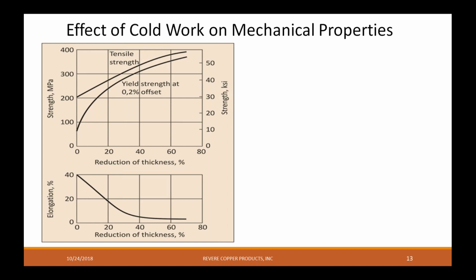And then your elongation at the same time is going to go down. So that's your ductility. So as the metal gets harder, it becomes less ductile. So at the same reduction, if you went from a 1/2 inch to a 1/4 inch, your elongation will go from 40% down to about almost nothing.